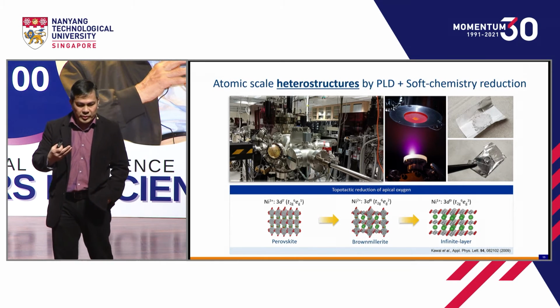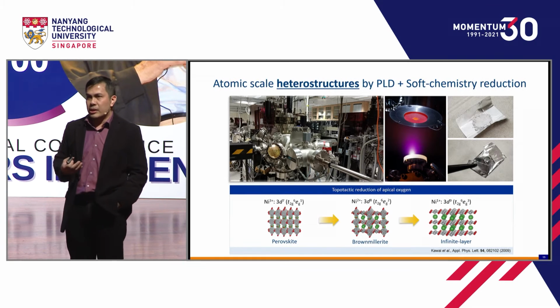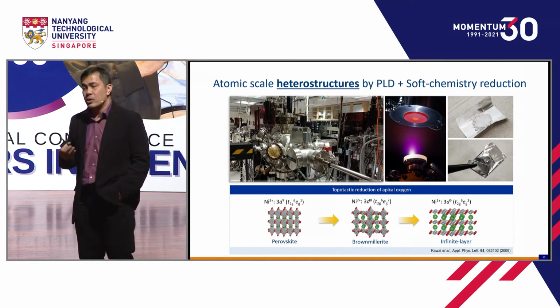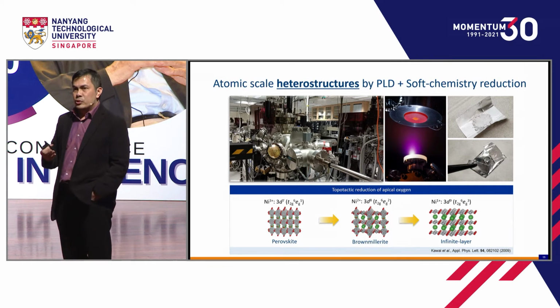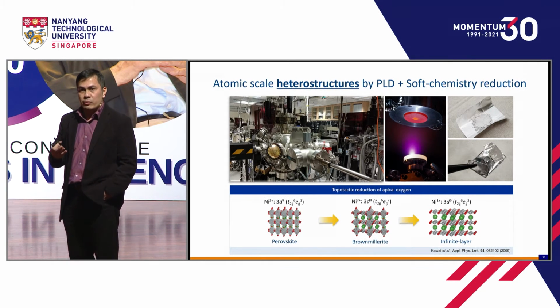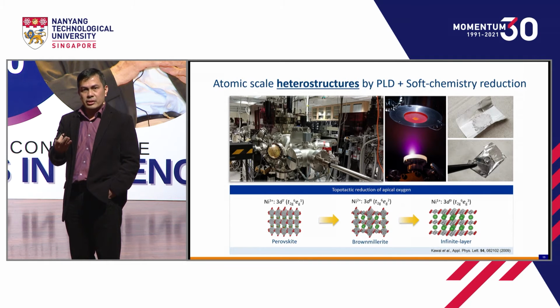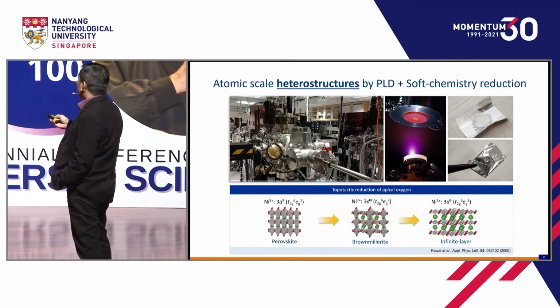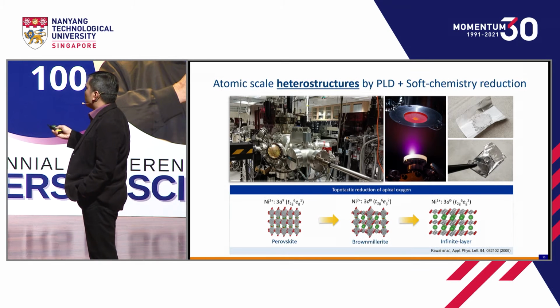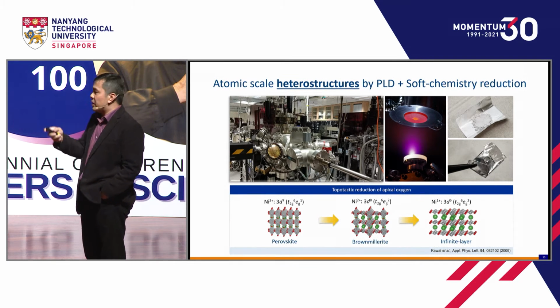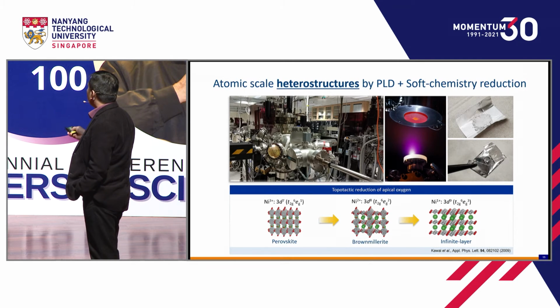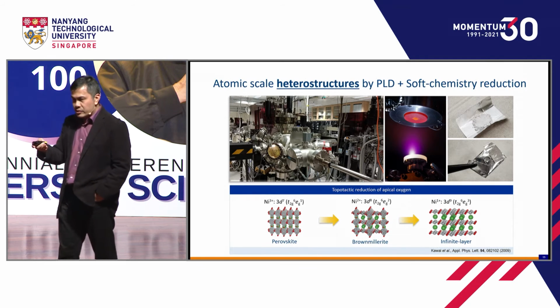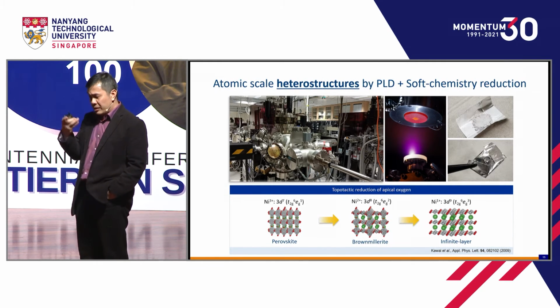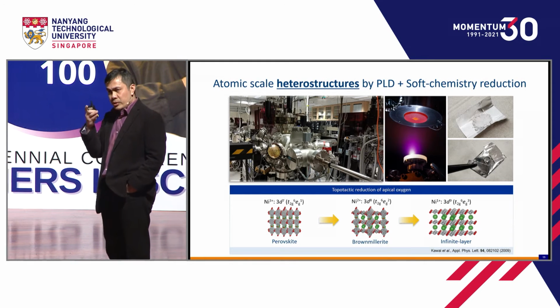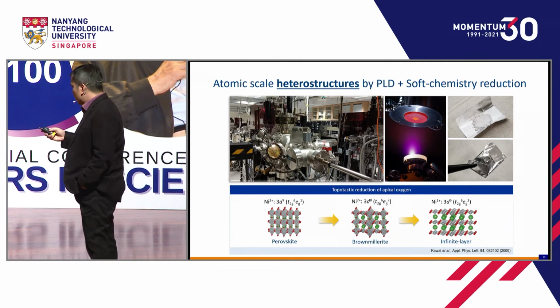In the community, this controlled way has been developed in the last 30 years or so, where you can make heterostructures using a substrate. Having a substrate looks like a very critical point, where you can hopefully stabilize the infinite layer structures when you do this removal of the atoms, okay? So this is an equipment that we have in our lab. This is a vacuum chamber where you can grow these crystals atomic layer by atomic layer. This is how the inside of the chamber looks. And then after you create these structures, you can try to do so-called topotactic reductions, where you do the soft chemistry of removing the atoms. And somehow this process works.